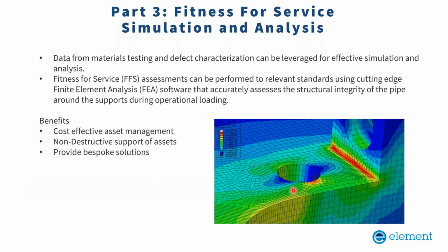The data from material testing, which was collected during on-site and in-lab analysis, was used for finite element analysis to do in-service remnant life assessment. The fit for service assessment or remnant life assessment was performed as per the industry standard. We have used advanced finite element software to facilitate this analysis, and detailed modeling and simulation was done to simulate the accurate operation condition and the corrosion condition of the pipe.